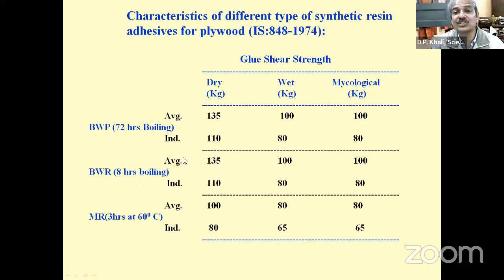Now, this is the test of strength, how much strength it has got. Now, how to test durability? For durability, these two tests have been simulated in the lab, as some accelerated tests. The first one is the wet test. What does wet test mean? For BWP, the samples, like those I showed you in the next slide, are kept in boiling water for 72 hours. After boiling for 72 hours, those samples are again subjected to the glue shear strength test. If they are able to withstand more than 100 kg, then we say that it meets our BWP.